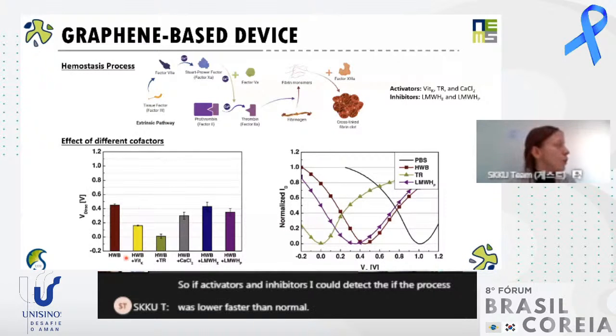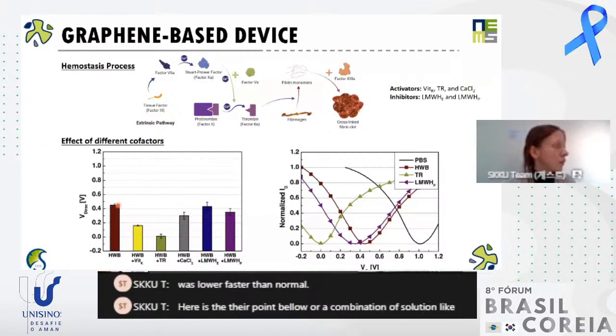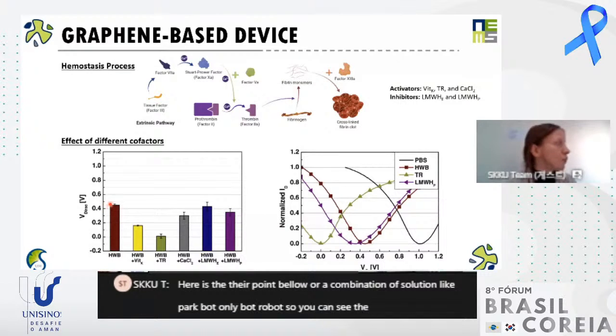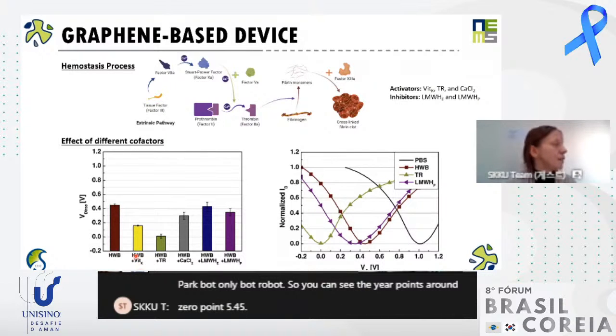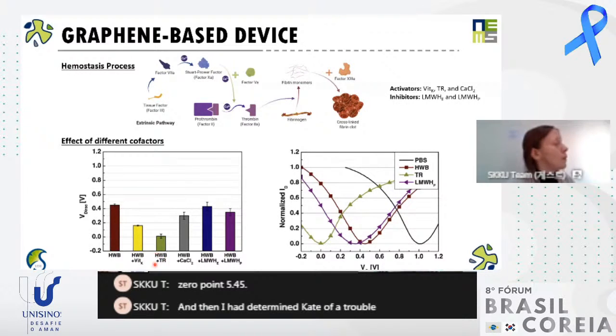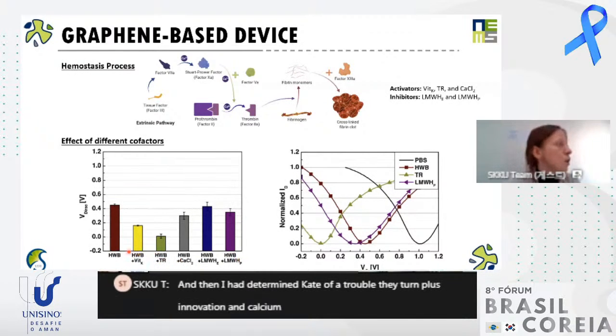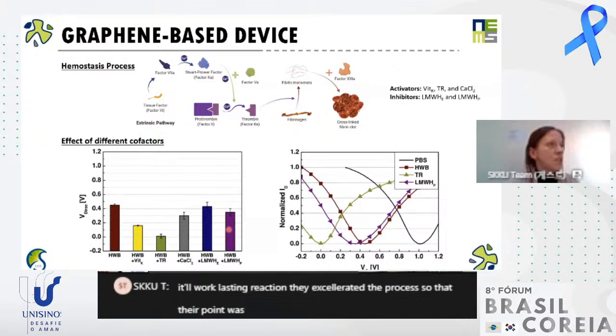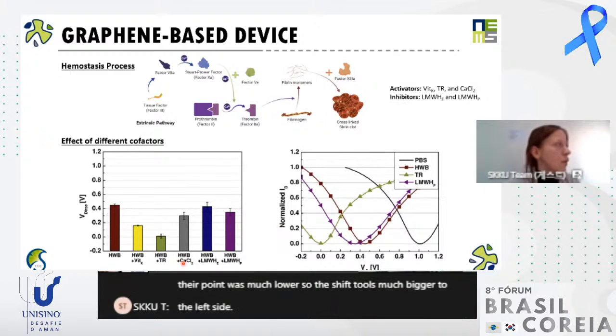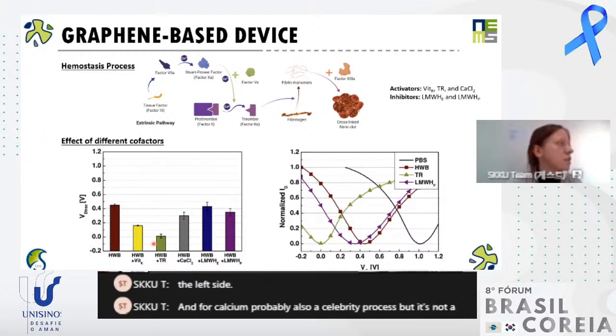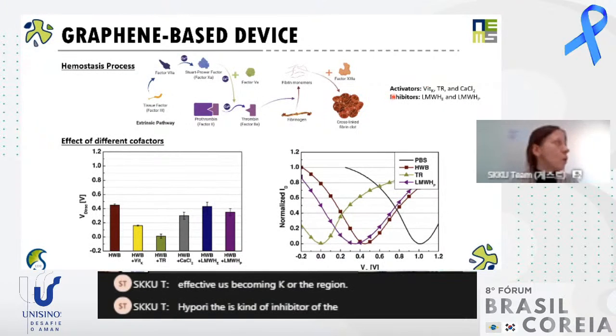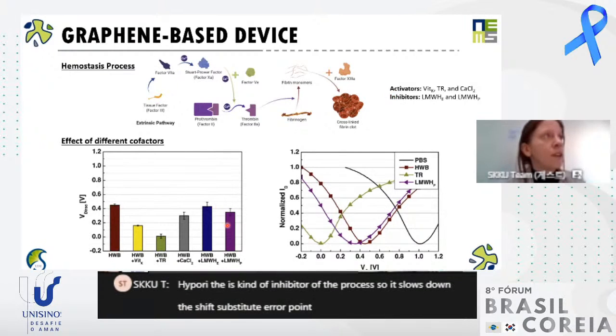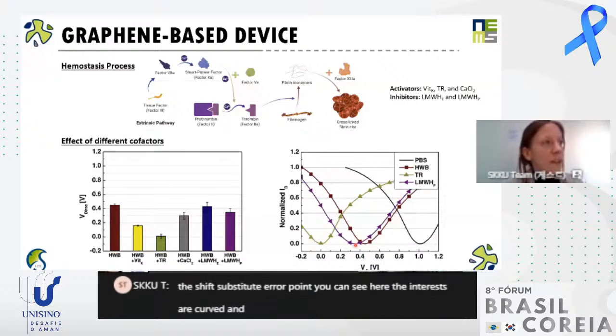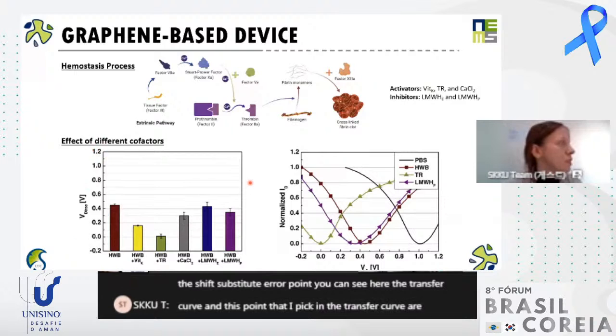Here is the Dirac point value for different combinations of solution, like first blood, only blood, raw blood. So you can see the Dirac points around 0.5, 0.45. And then I added vitamin K, the thromboplastin reagent, and calcium and two heparins. So vitamin K and thromboplastin reagent accelerate the process. So the Dirac point was much lower, so the shift was much bigger to the left side. And calcium also accelerates the process, but it's not as effective as vitamin K or the reagent. And heparin is a kind of inhibitor of the process, so it slows down the shift of the Dirac point. You can see here the transfer curve, and these points that I picked in the transfer curve are shown in this graph, like a bar graph.